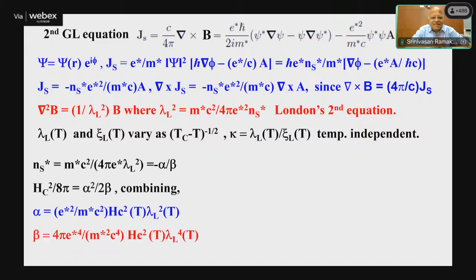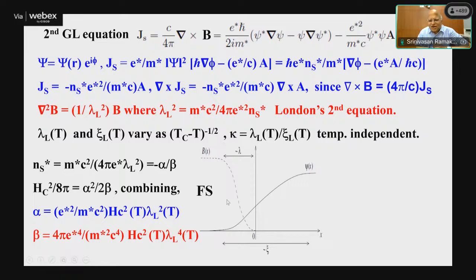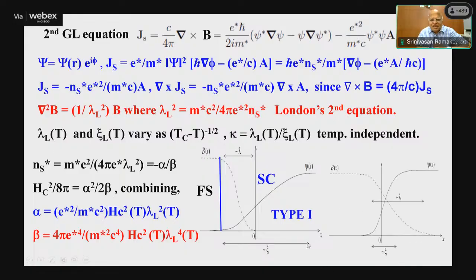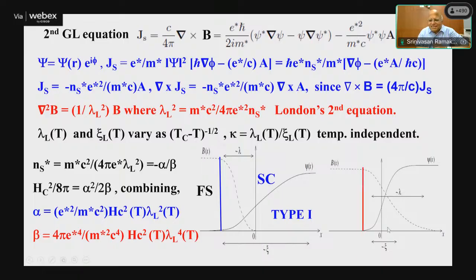So it varies as (T minus Tc) to the whole power half, and then you can define a temperature independent constant called the Ginzburg-Landau constant, kappa, which is the ratio of lambda L by xi T. And so what you will see is there are two kinds of superconductors naturally coming out of the Ginzburg-Landau theory. One is a type 1 superconductor where xi is greater than lambda. Then there is another superconductor where xi is less than lambda.